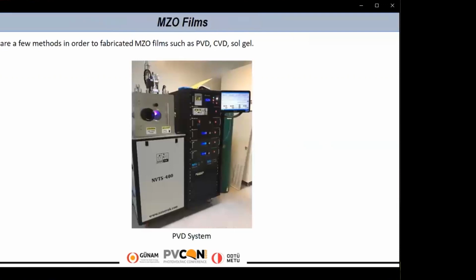There are a few methods to fabricate MZO films, such as PVD, CVD, sol gel. MZO films were fabricated using the sputtering technique in PVD. 10 different sets of samples with different thickness. We fabricated MZO films from 50 nanometers to 500 nanometers. The reason we investigated such a large range is to find out the best film thickness in terms of optoelectronic properties. By the way, we didn't apply any pre or post annealing to the fabricated MZO films.